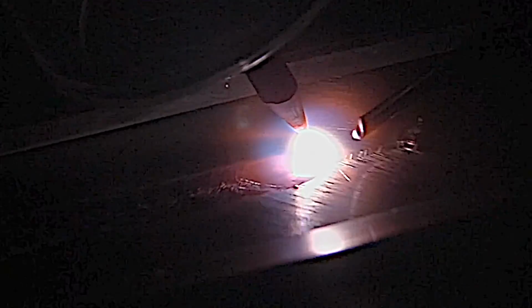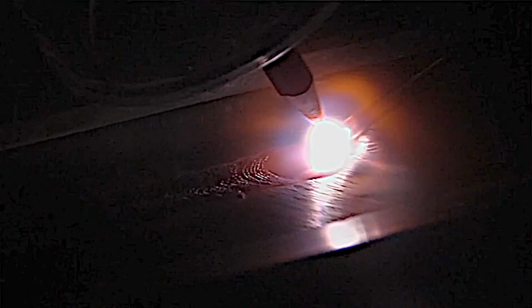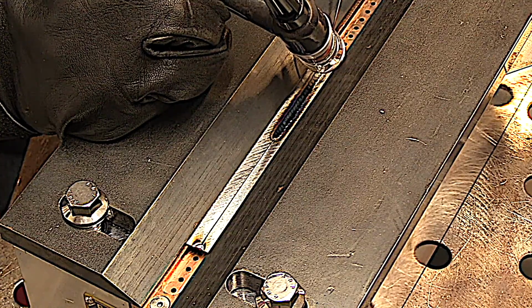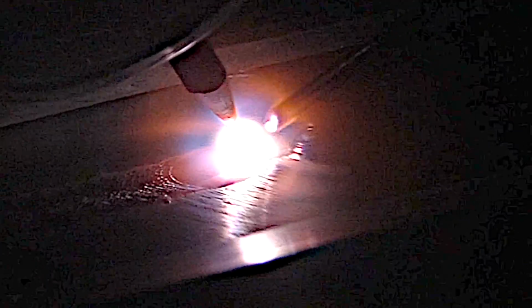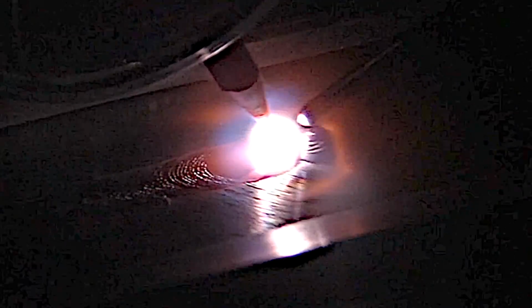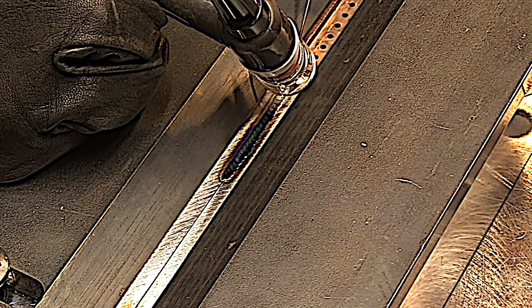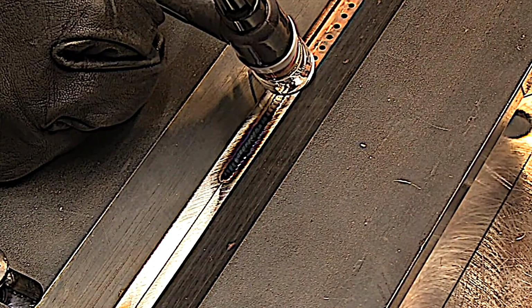Welding to that tack where I added a few extra little dabs, I'll show you that right now. Right there I start to taper off. You can see I did not even come close to blowing the end away because I had a little extra heat sink there, a little extra dam of extra mass, of extra metal with that extra few dabs on that tack. Here it is in slow motion. As soon as I get right about here, I start backing off the pedal, taper off and back up the arc a little bit, and it doesn't leave a crater crack or a mark or a crater hole or anything like that, and keeps the end intact.